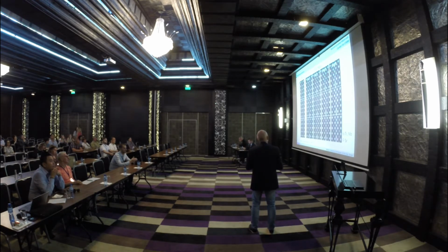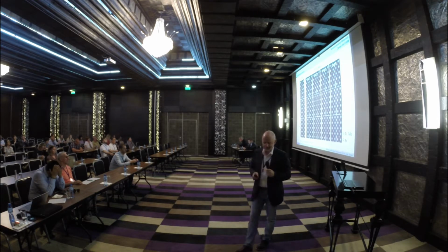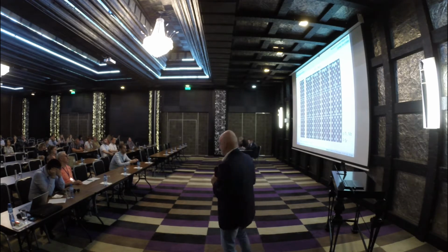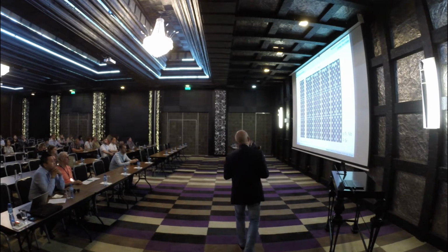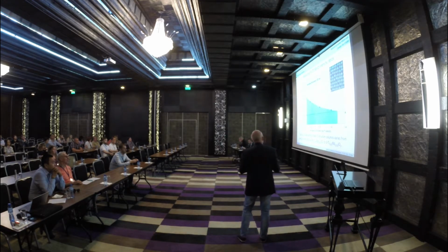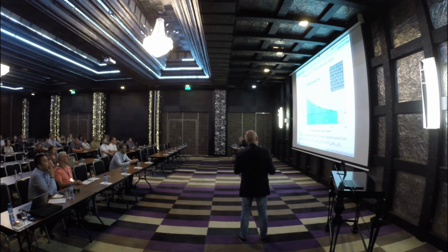So we did some imaging simulations to see how the intensity ratio between the A and B sites would change if we were increasing the niobium content. We found that in our material, these are the measured ratios, and this is converged to the compositions on the B site.